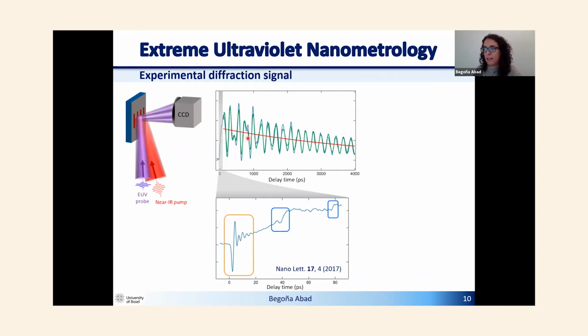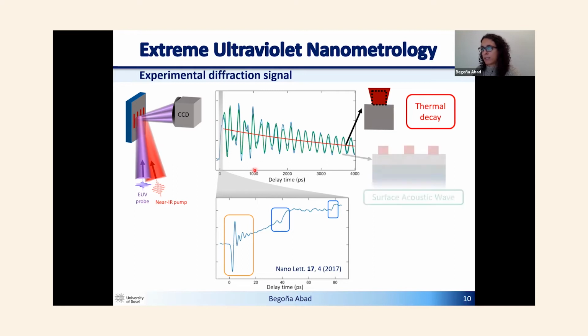Here is the typical trace or raw data that we get. This is the system. We pump with our infrared pump and we probe with the EUV probe and record the diffraction pattern. This is the typical signal that we see. And as I was saying, first we see the thermal decay, but there are some acoustic waves superimposed that are given by the nanolines acting like hammers and creating these surface acoustic waves whose frequency we can extract from the Fourier transform of this signal.